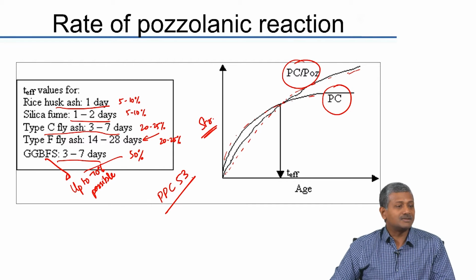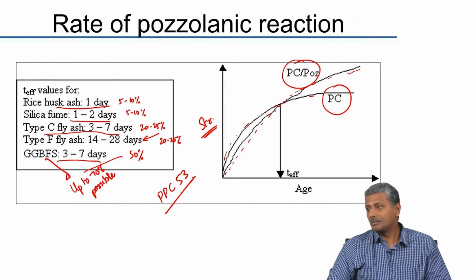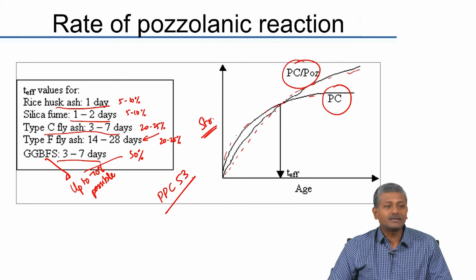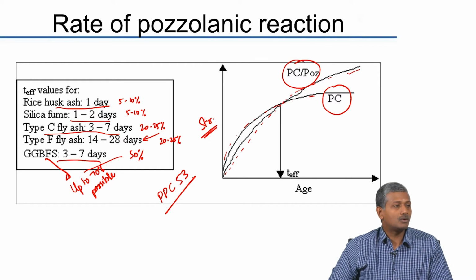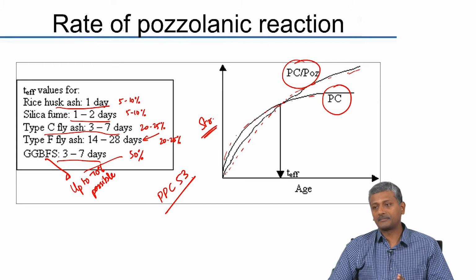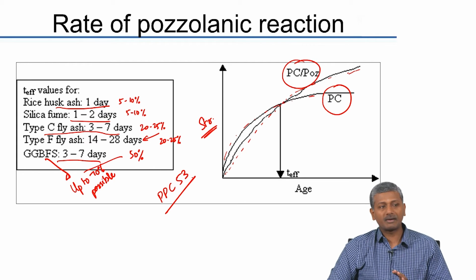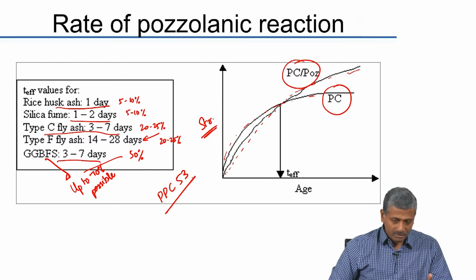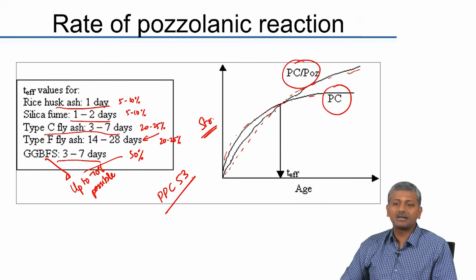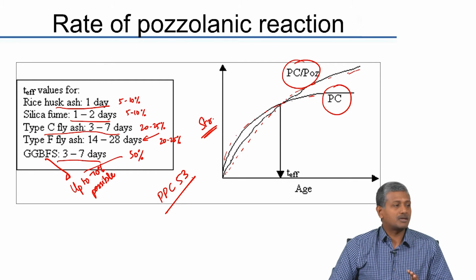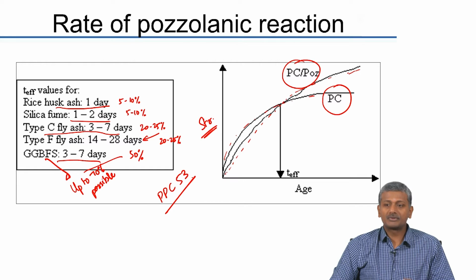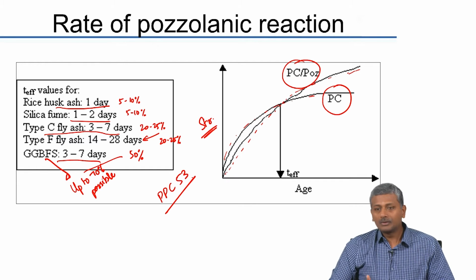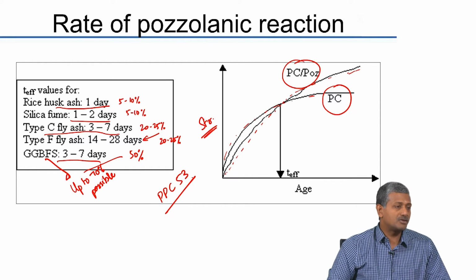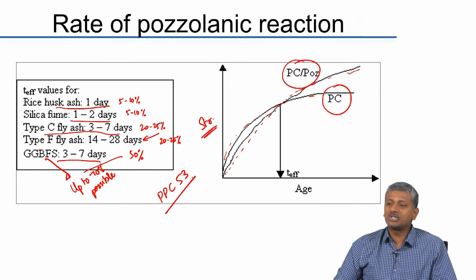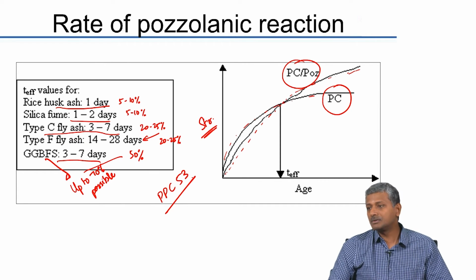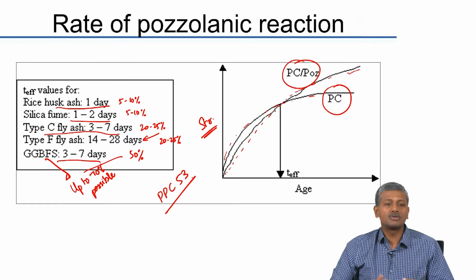If you really look at the code for PPC, Portland pozzolan cement, you will actually find that the strength gain requirement only matches that of a 33 grade cement. For a PPC, the strength gain requirement is only that of a 33 grade cement. But without applying their minds and just thinking about the customer's demand, the cement company started producing 53 grade PPC. So, that defeats the purpose, because you do not have the benefits of low heat of hydration anymore. Just in an attempt to achieve that high strength, you are trying to curtail the main importance of your product.